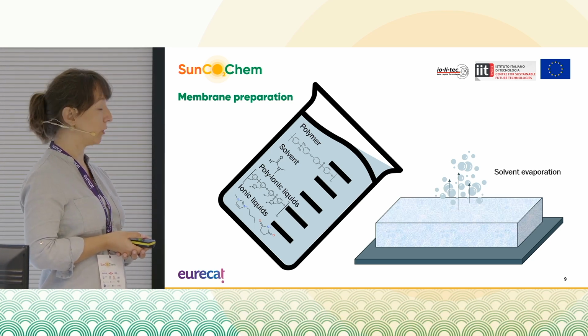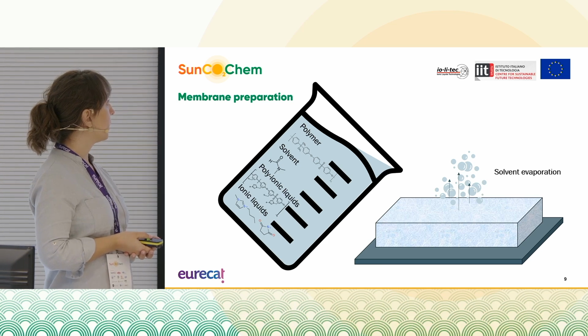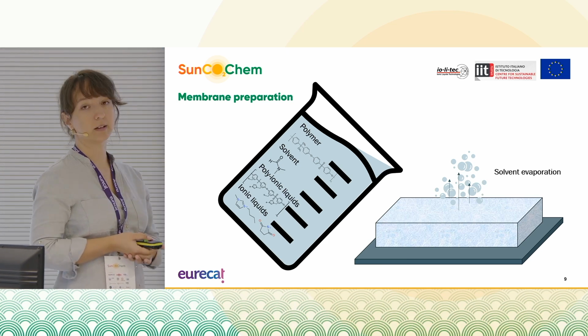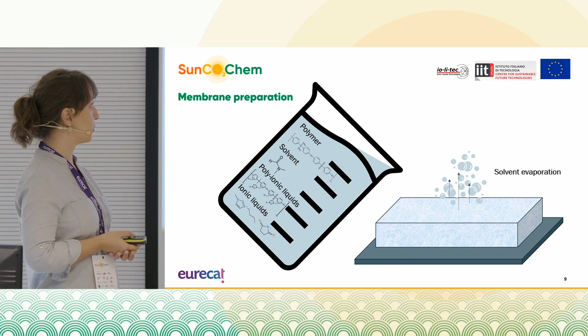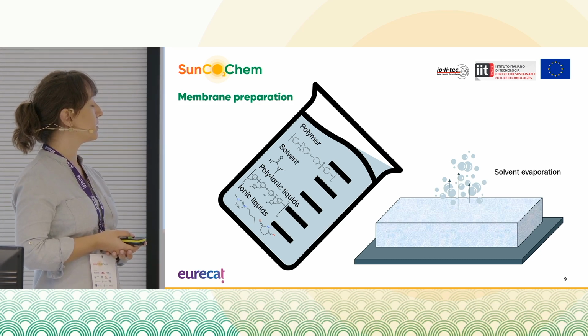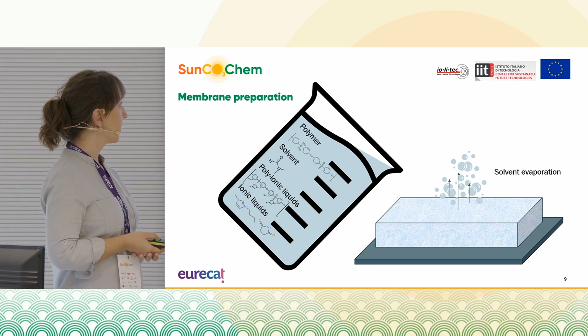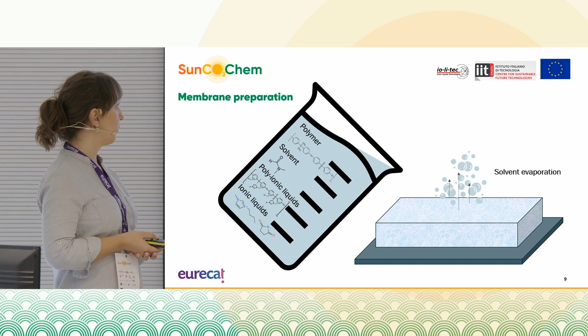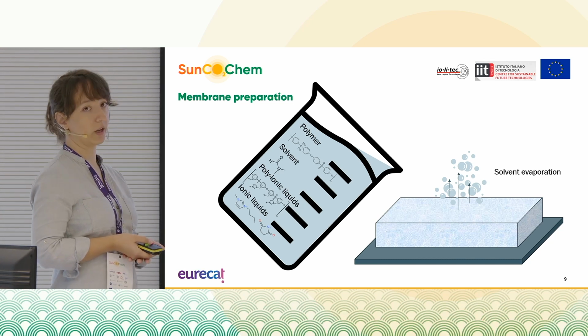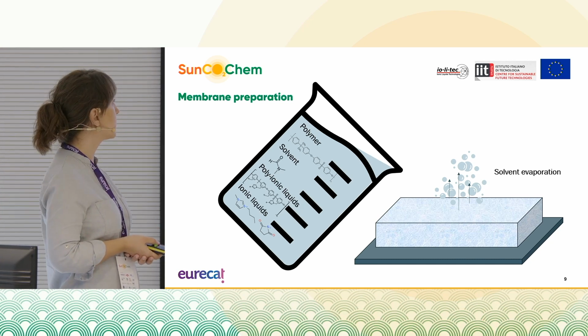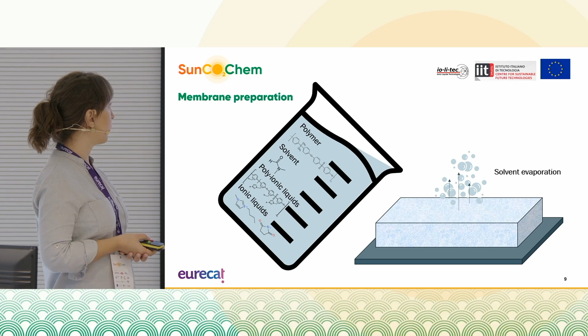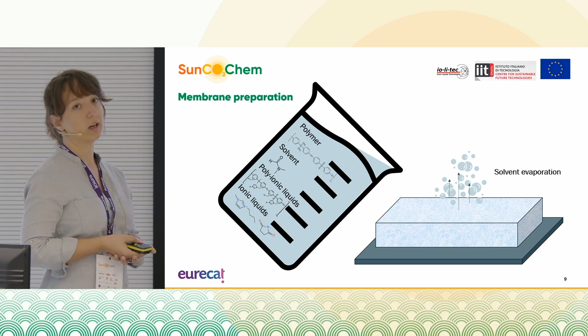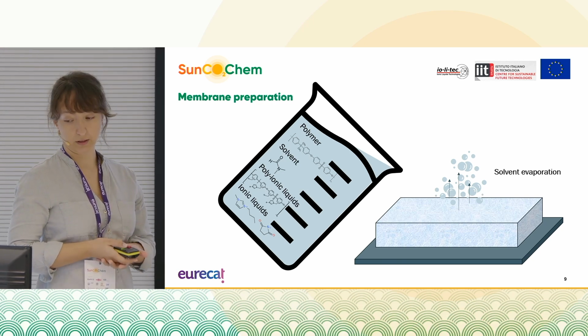In the polymeric solution, we introduced the polymer that we used, that was unmodified, it was polysulfone. It increased the mechanical stability of the membrane. We dissolved it in an organic solvent. Then we also added the polyionic liquids previously synthesized. And we also added a free ionic liquid in order to even more increase the affinity of the membrane.